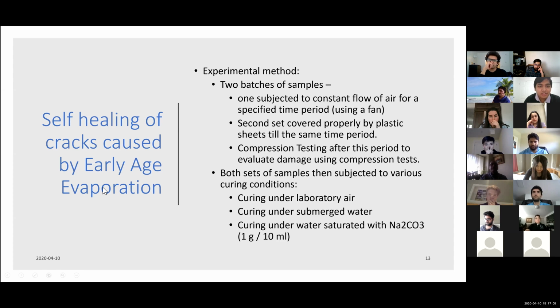Then this is self-healing of cracks caused by early age evaporation. So the thinking behind this is, let one batch of samples, I subject them to a constant flow of air for a specified time period, and the second set I covered with plastic sheets, so they are not subjected to evaporation at all. While one is under a constant flow of air for a specified time period, which I usually took as 1 or 2 days. And after this, I took out both samples and I tested them in compression to evaluate what damage this difference has done. Then after I have evaluated the damage, I again put them under 3 different conditions and reevaluate what the strength becomes.